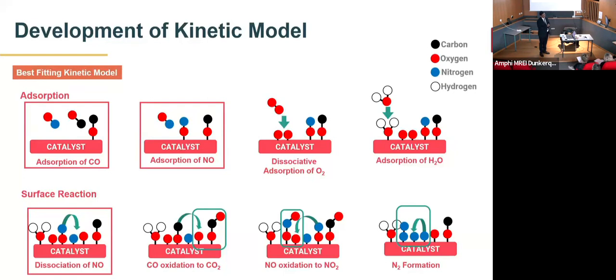So supposing that you choose the best thermal treatment, can we really imagine that this characteristic will remain unchanged during normal use of the catalyst, knowing that the chemical composition of the gaseous mixture will change, and therefore its redox potential as well, making these ratios change with time? You tested the activity of the catalyst for a few weeks, but isn't there a problem? Is that an issue, or do you think it's not a problem at all?